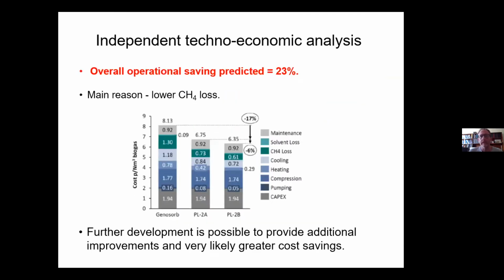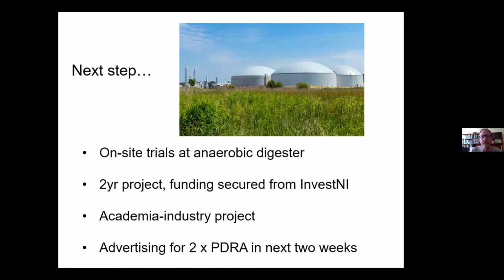We also got a techno-economic analysis done on this by some independent consultants. And they said that if you could just change the setup, so instead of putting in the industrial solvent, you put in the porous liquid, what difference does that make? They predicted you can get a 23% operational saving for various reasons, different pumping energies, but also you lose less methane in the process because you have a more selective solvent. So next step there is we're going to on-site trials to see if we can do this with real biogas, and we're looking at other opportunities for CO2 capture as well. We've got some quite exciting things going on there.